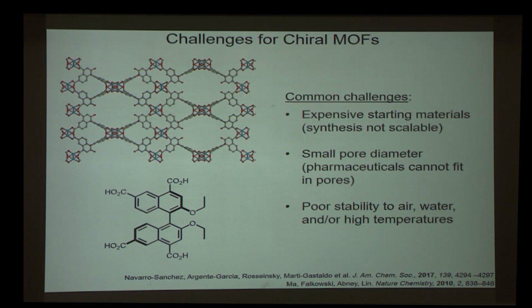So although a lot of work has been done with chiral MOFs, there are some common challenges that are encountered in these materials. And to the best of my knowledge, no published chiral MOF simultaneously overcomes all of these disadvantages. The first common issue is that these materials are often synthesized from expensive starting materials, which means that they can't be made on a practical scale. It's also common that the pore diameters are small in these chiral MOFs, and pharmaceuticals tend to be quite large, which means they can't even fit into the pores. Finally, a lot of these materials have poor stability to air, water, or high temperatures.